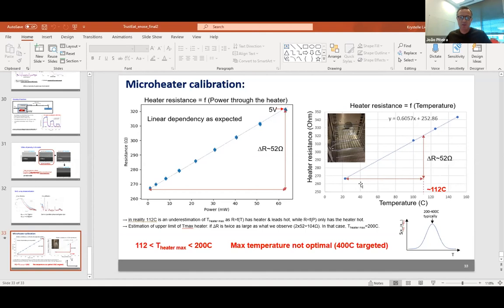Okay, so you extrapolate then for the higher temperature. Right. And so that gives us 112 degrees, but we know in reality it's slightly higher than that, because in one case you're only heating the heater, in the other case you're heating the entire chip. So we know this 52 would correspond to a slightly higher resistance here. We don't know exactly how much, but we're saying, okay, maximum twice this amount. And for twice this amount, we would reach 200 degrees Celsius. So we know we're reaching somewhere around this temperature, even though it's not clear.